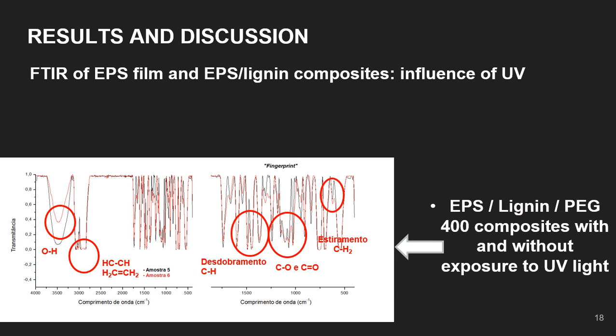With respect to polyethylene glycol samples, sample 6 demonstrates an opposite effect to that seen in sample 4 with respect to the hydroxyl band. That is, it has been shown to reduce with the exposure to UV radiation. Perhaps the photochemical treatment promotes interactions between the polyethylene glycol hydroxyls that are located at the end of the chain with other substituents of the composites.